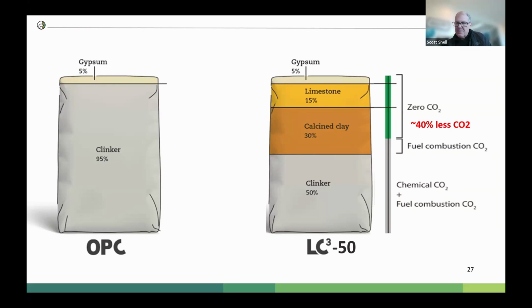Now, this is not limestone that goes through the kiln. This is just ground up. So it's very, very low carbon. In both of them, there's about 5% gypsum added to control the set time. In LC3-50, there is still some fuel used to calcine the clay. So instead of getting a 50% reduction, you get about a 40% reduction in CO2 emissions.